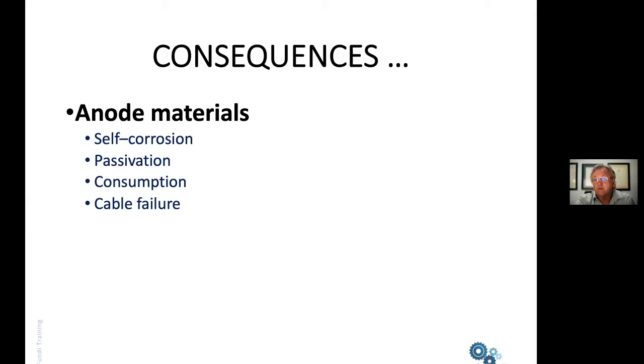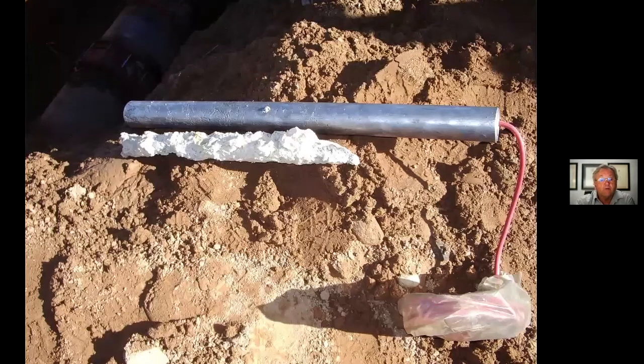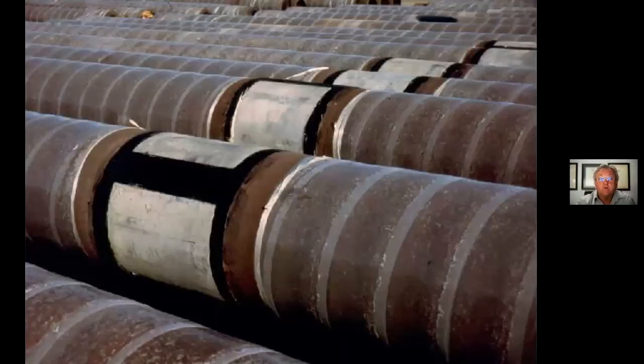You cannot use conventional cables in chloride environments like seawater or brackish water or brack soil even, because of the generation of chlorine gas. So here's an anode that corroded away by itself, never mind providing any protection. These anodes were used on an offshore structure, and there was a hasty decision made to merely continue the same principle of corrosion protection for the 2 kilometers of onshore pipe. Problem is, when you put an aluminium anode onshore without chlorides around, it goes to sleep. And that became, again, a very expensive, incorrect material selection.